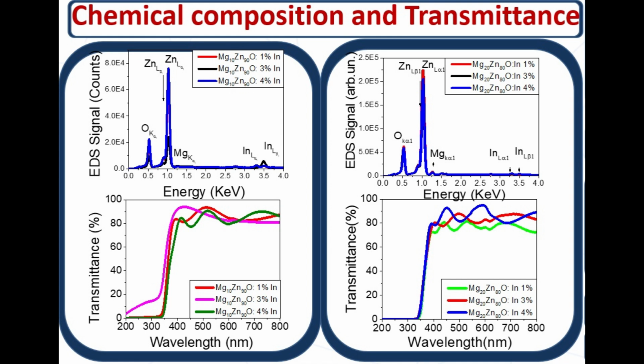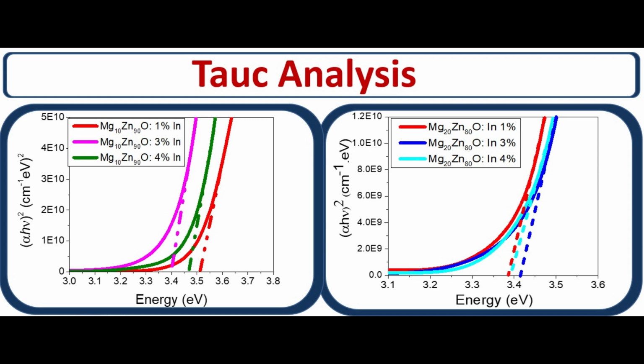EDS spectrum analysis revealed the presence of indium, zinc, magnesium, and oxygen in two distinct sets of samples with magnesium concentration of 10% and 20%. On the other hand, the transmittance exhibited a sharp absorption edge for all samples. In addition, a noticeable shift occurred at the fundamental edge for varying concentrations of indium, exclusively observed in magnesium 10% samples. This shift was less pronounced in samples with 20% of magnesium.